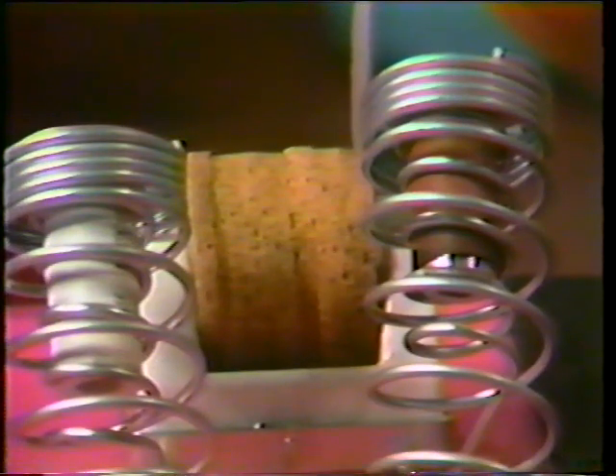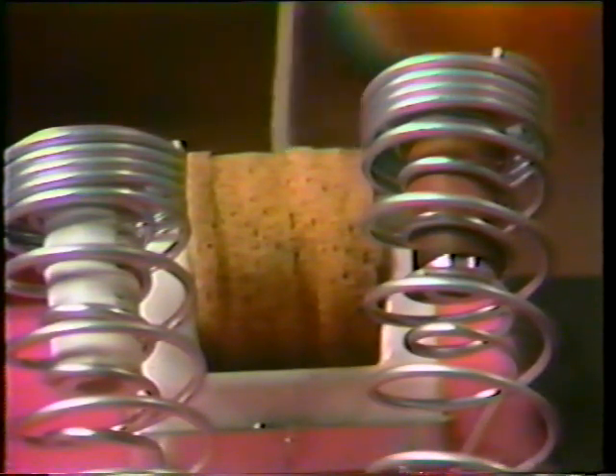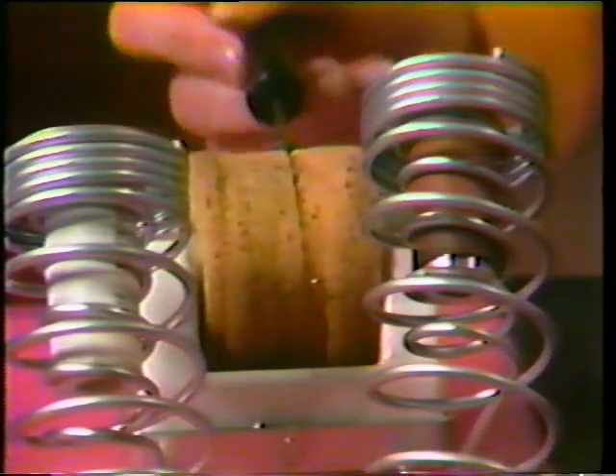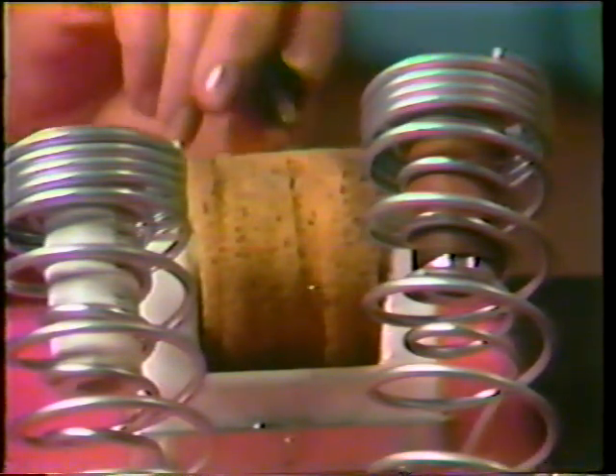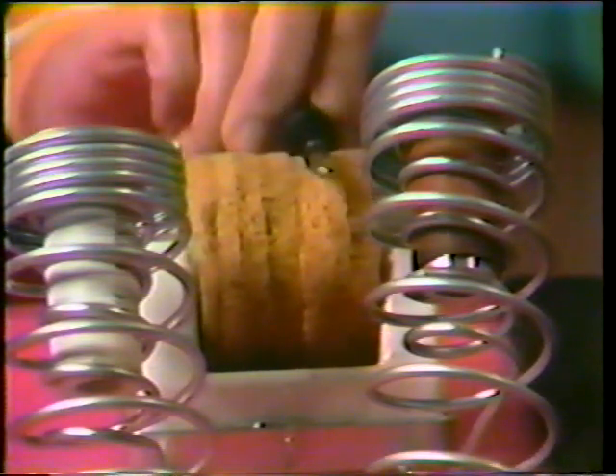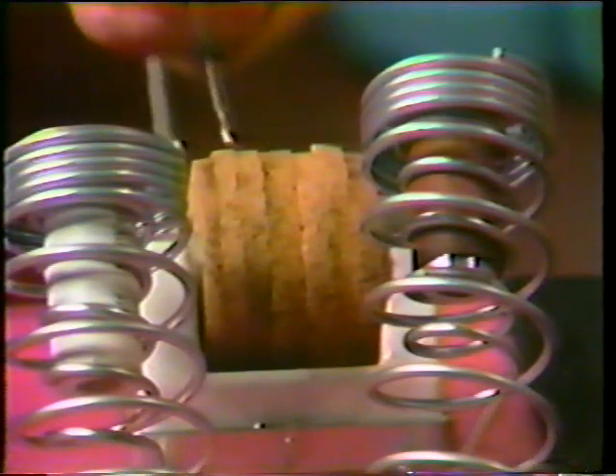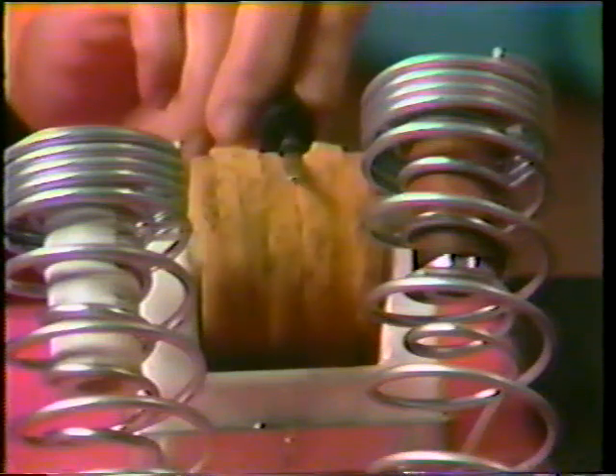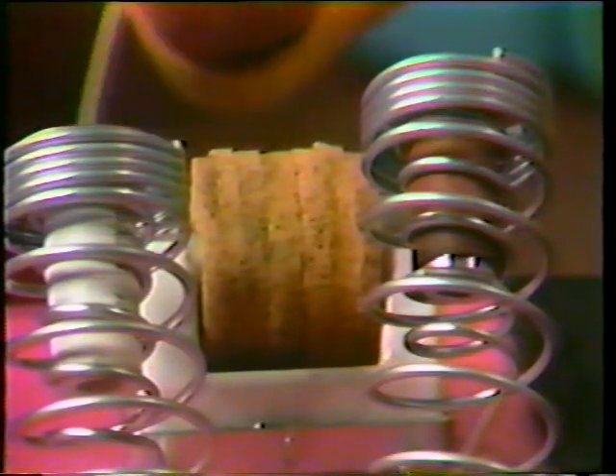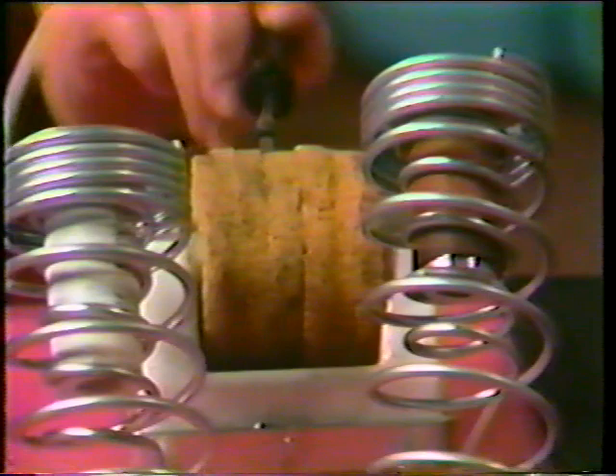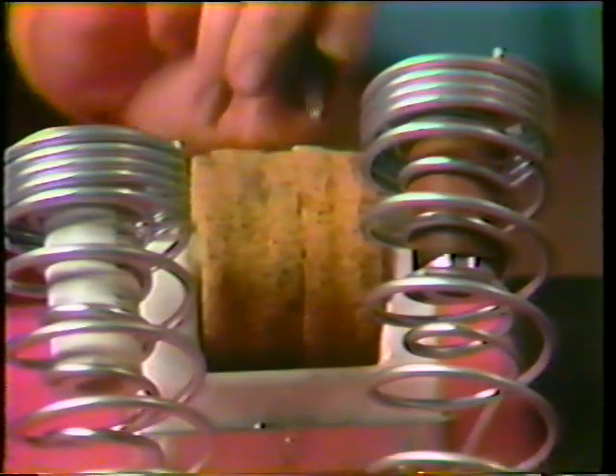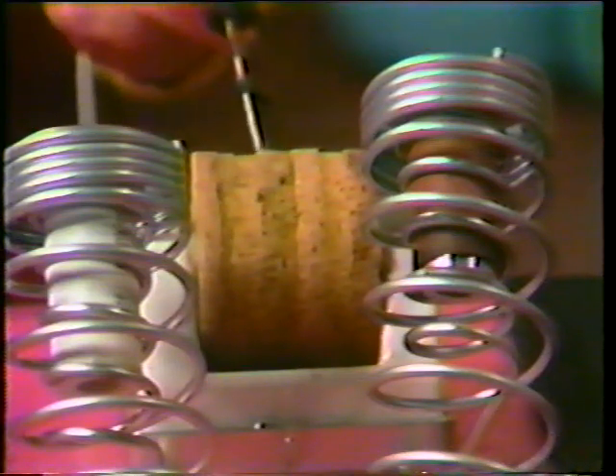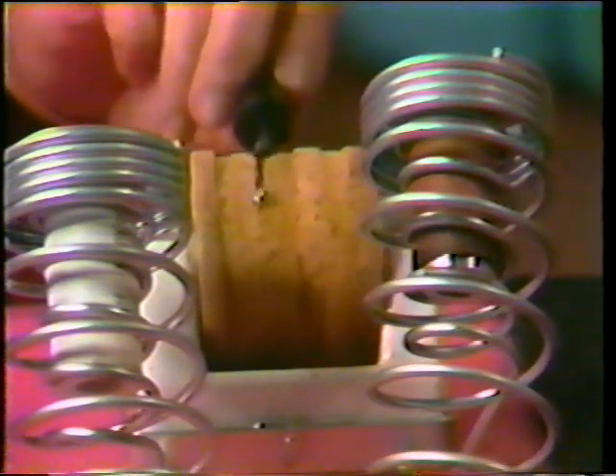The best cleaning sponge for this purpose is a vertical segmented rotary sponge held in a non-corrosive container. The tip is passed between the vertical segments of the sponges, which exerts a uniform and repeatable cleaning action each time it is used. Notice that the operator also rotates the soldering iron as it is pulled through the sponges. The rotary sponges revolve during the cleaning process and provide a fresh, clean sponge area for subsequent cleaning.